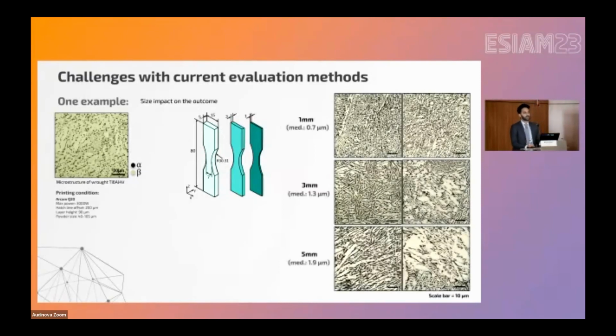After fabrication, we checked the microstructure. You can see in each row, you have one thickness from 1 to 5. If we compare the grain size of these three specimens produced with the same feedstock, produced with the same process parameter, and in the same batch, we can see going from 1 to 5 millimeter thickness, the grain size is approximately 3 times larger. And this is the median size. The maximum is even higher.